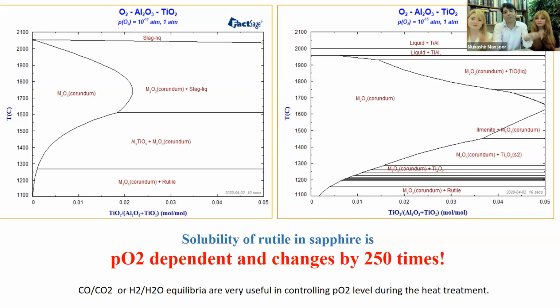So this is a beautiful harmony between experiment and calculations on how the solubility of rutile depends and changes based on the oxygen fugacity in the furnace. So for the people who do sapphire treatments as a hobby or professionally, I highly recommend that you do not ignore the impact of oxygen and the oxygen concentration.